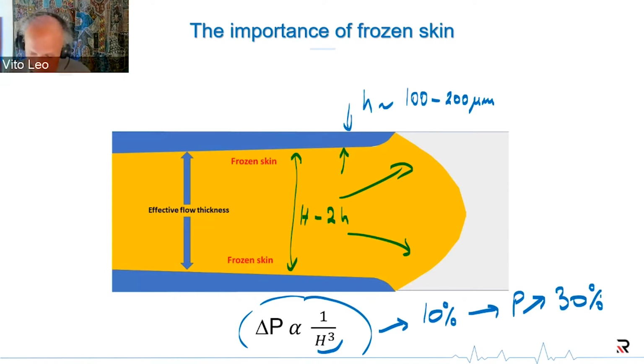And if you can somehow reduce the frozen skin, you could get a huge benefit. Now again, 200 micron is 10% of 2 millimeters. Then you have one frozen layer on each side. So with 100 micron on each side, you lose 10% of a 2 millimeter plate.